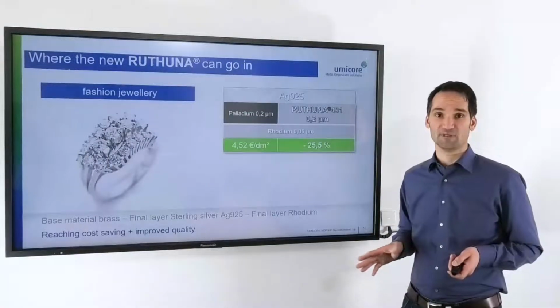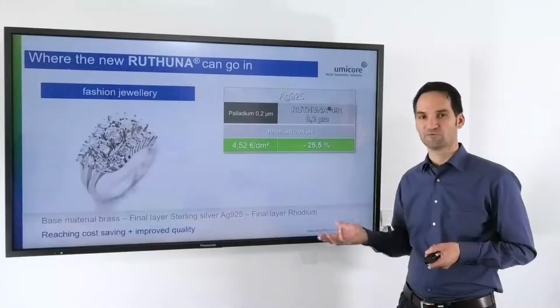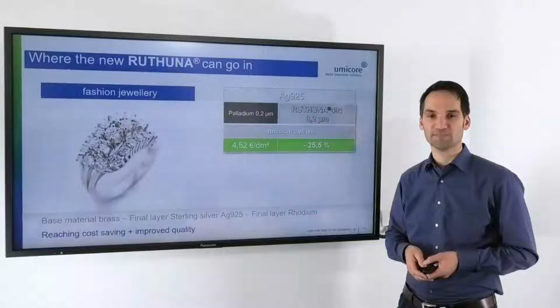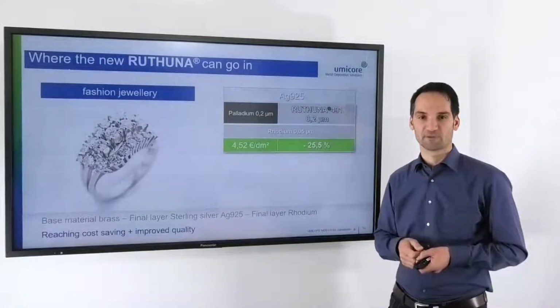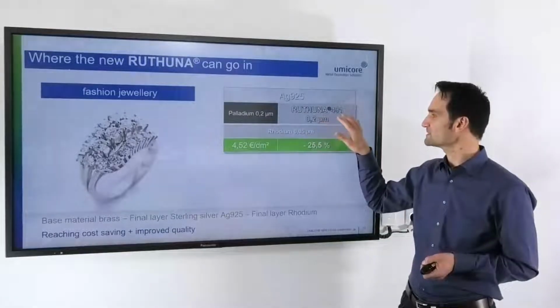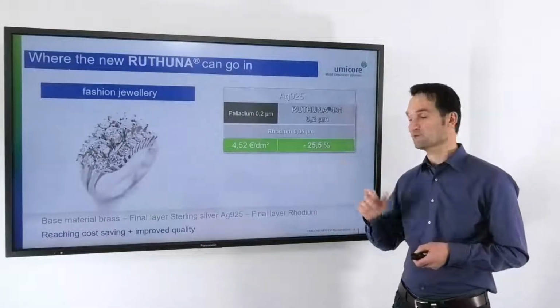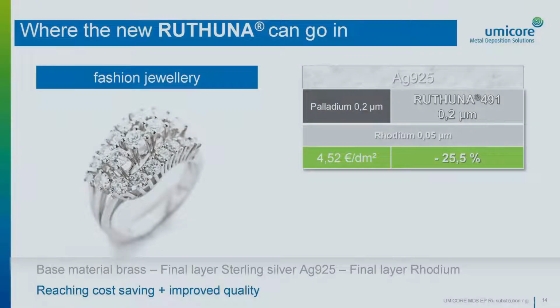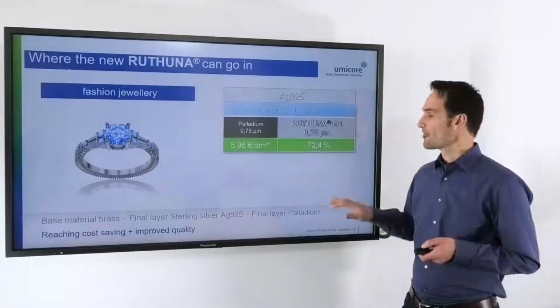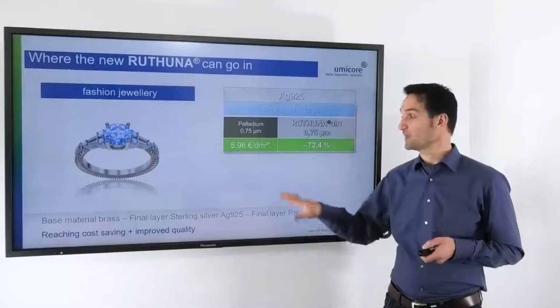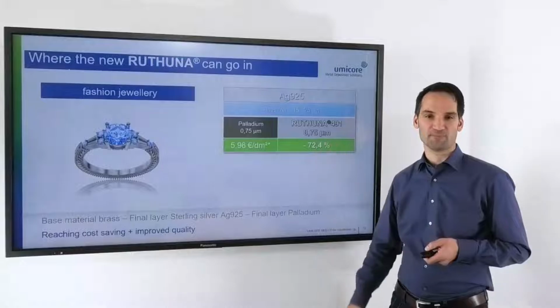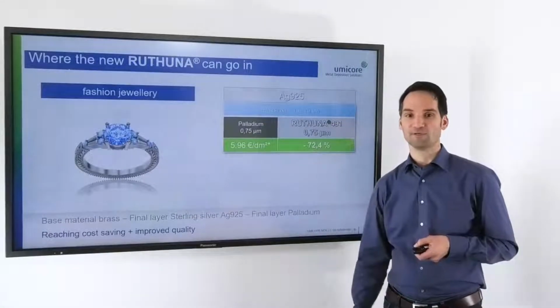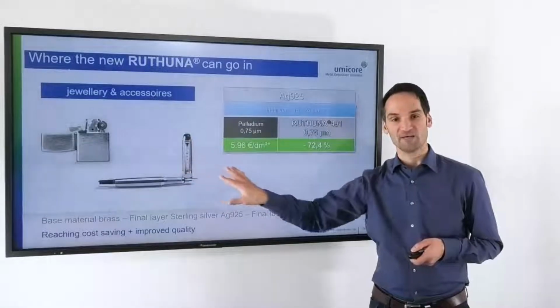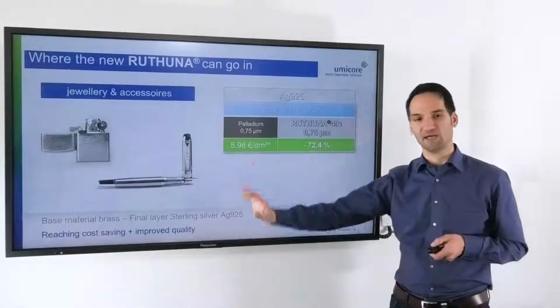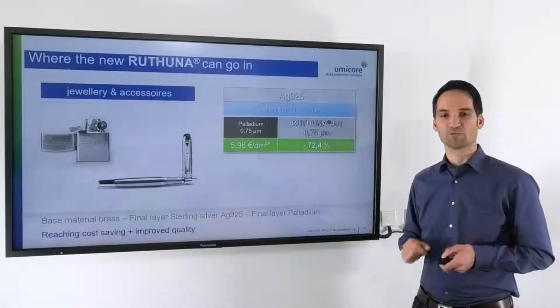A standard application in fashion jewelry: sterling silver flashed with rhodium, but having a palladium layer in between to have the corrosion and diffusion barrier. In future, it can easily be replaced by the RUTHUNA 491 and give you a saving of more than 25%. If you have an application which has the final layer in palladium, you can directly interchange it with the pure ruthenium and the saving is more than 70%. These applications are quite often done in jewelry, but in the accessories field as well, like on lighters and writing utensils and so on.